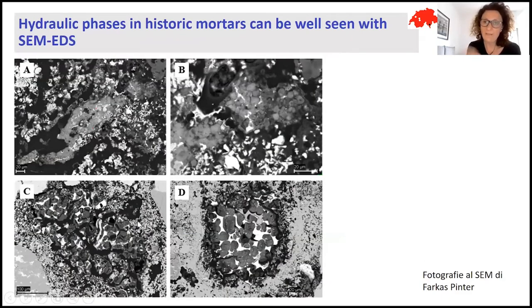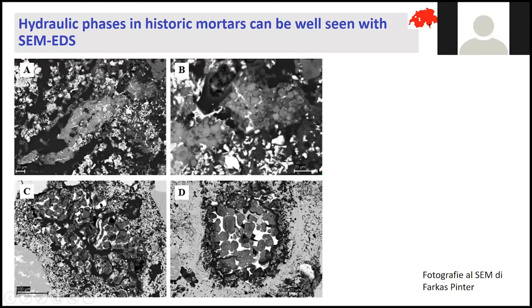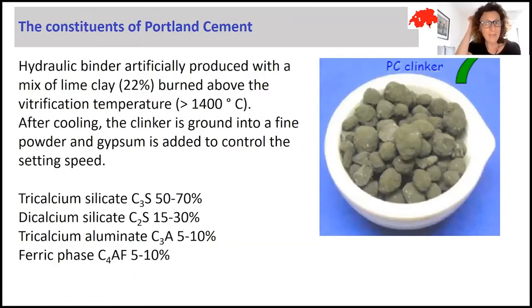Another possibility is to use higher magnification and study these binder-related particles, so this clinker, with the scanning electron microscope. And also in this case, I can distinguish, for example, the calcium silicate hydrate from the aluminate and the iron part of the clinker. The same can be done for a Portland cement. The higher temperature of the kilns makes the production of tricalcium silicates. So by studying this clinker, I can distinguish an old cement from a Portland cement.